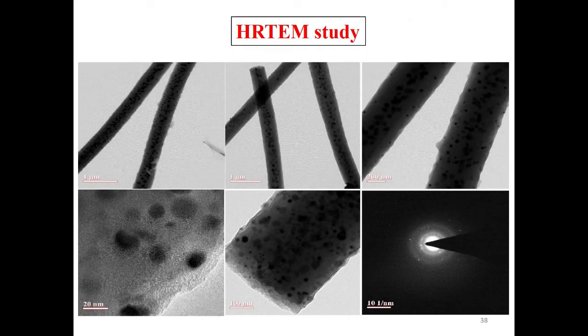This is the high resolution transmission electron microscopy, showing the polycrystalline nature with a diffraction pattern, and the decoration of that particular copper nickel nanomaterial is observed over the carbon nanofiber.